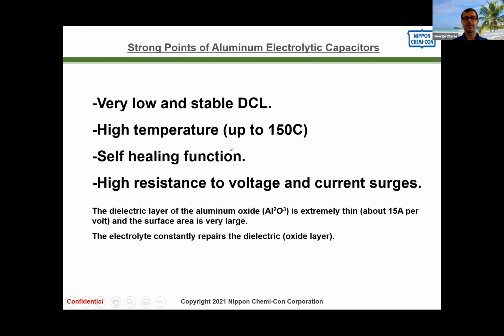High temperature ratings. Right now we can offer up to 150 degrees C rated electrolytic capacitors. 1,000 hours right now, 2,000 hours will be very shortly. They have a very good self-healing function, which I mentioned earlier. And they are pretty much, I don't want to say immune, but they have a high resistance to voltage and current surges.